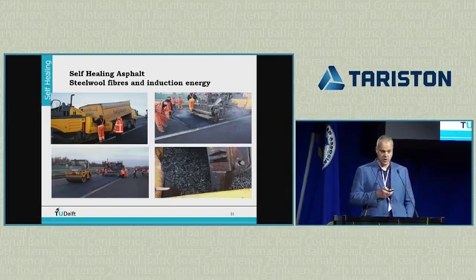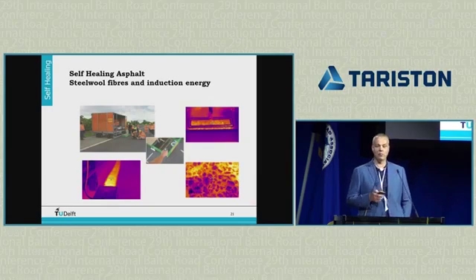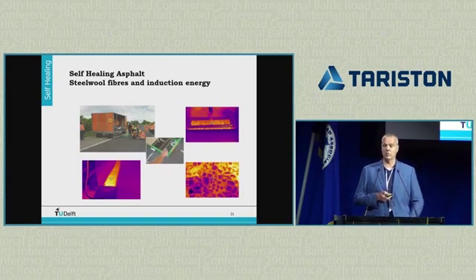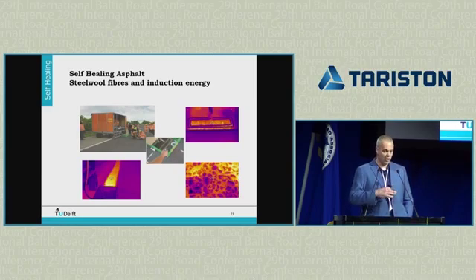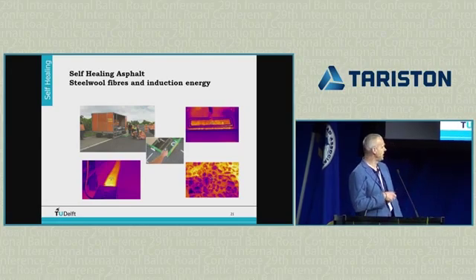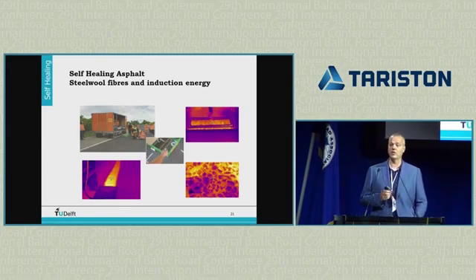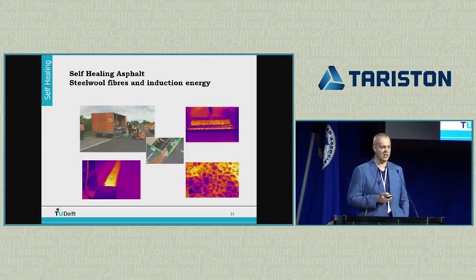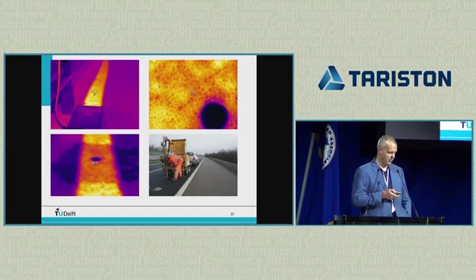So then after 4 years, we thought this is the time we have to do the first treatment. That came out of our lab research. After 4 years, we went there with a small induction machine, a prototype that we built, to heat up the asphalt. So you go there with your induction coil driving over the surface, just a few centimeters above the surface. This heats up the steel wool, which heats the bitumen, but you don't heat up the stones, that you also see in this infrared image, that your stones actually keep cold, which is good because you don't want to heat up the stones, you don't want to put energy in there. And also the stones will cool down your asphalt as quick as possible. So it moves over and 15 minutes later it's cold again because that's what the stones do. So in this way you can close all micro cracks, all your stones are fixed again, and you can open the road and drive on.